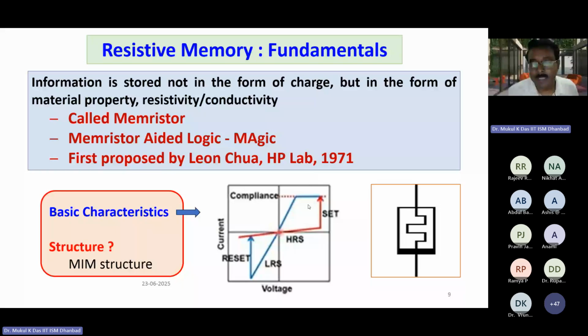So there is a hysteresis loop, and at the 0 point you can get a non-zero current. Earlier it was zero current. So to get the zero current, you have to apply some negative voltage again. That is, you have to apply a voltage in the reverse direction to completely break down the nanoionic film. This similarly happens on the reverse side also. So this is the origin of hysteresis.